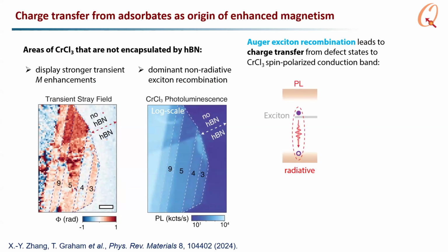The explanation is not all that interesting. It's due to defects in the band gap. We can prepare a sample where we look at the transient stray field and correlate it to the photoluminescence. In this sample, we cover half of the sample, and we see that when we see strong transient fields, we see very low photoluminescence from the chromium chloride. So it suggests that non-radiative exciton recombination leads to this effect.